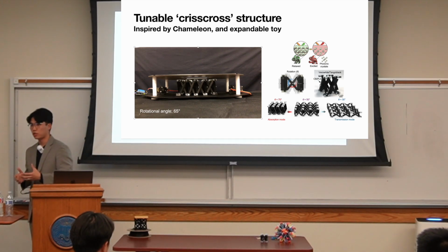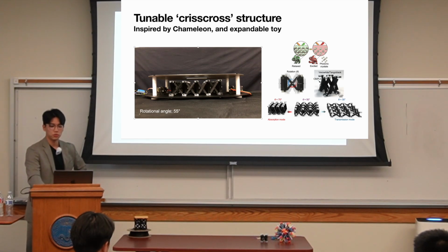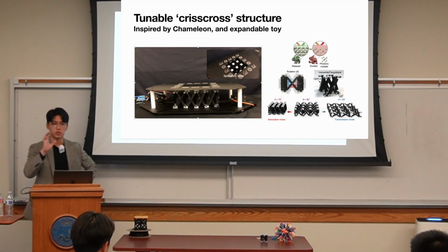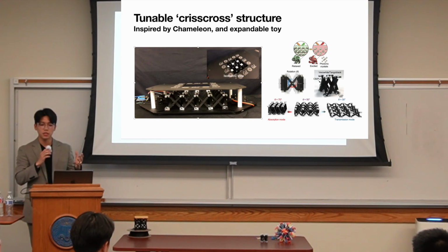For this crisscross structure, I had a hypothesis of making this tunable structure out of a truss made of carbon black PLA and other parts with transmitting material. By changing the position of this crisscross structure, we can probably switch between the absorption and transmission mode.